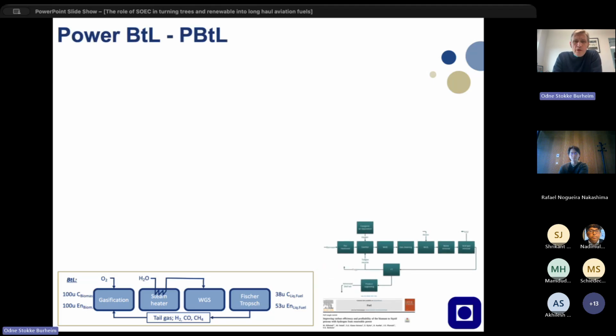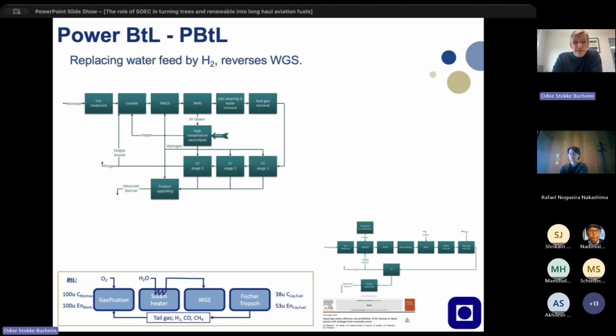Now we talk about power BTL. That's essentially when instead of feeding water into the water gas reactor, we're feeding hydrogen. So then that becomes a reverse water gas shift reactor, and you can see that here. It goes through the same cleaning procedures, and because of the balance between carbon monoxide and hydrogen, it makes sense to have 3 stages of Fischer-Tropsch, which gives products.